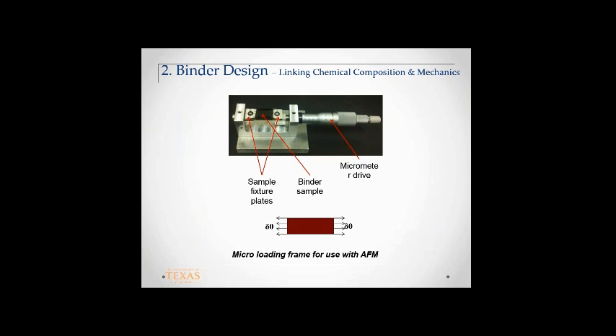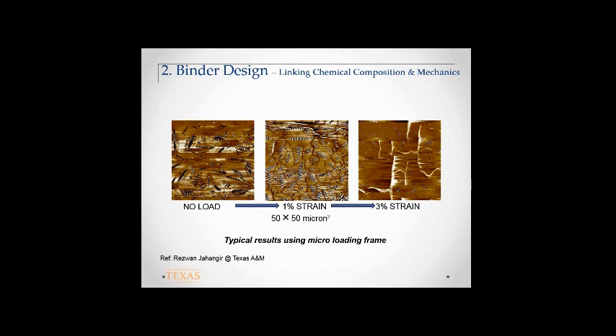So this was a mold we prepared, and we shipped it to Rizwan with some binder and said, would you stick this when you're running your tests under a microscope? It's a simple strain device. What you do is you have a binder film here. You apply a constant strain, and once you apply the strain, you let the binder relax all the stresses, you go back and image it. You'd see that this is under no load condition; after 1% strain, after 3% strain, you'd see that these features start developing.